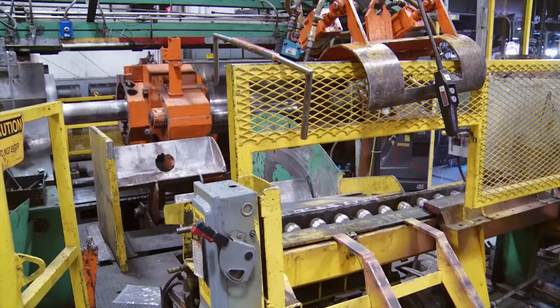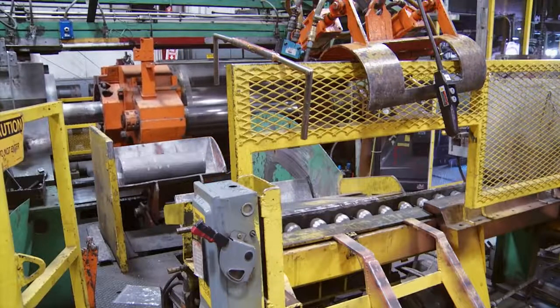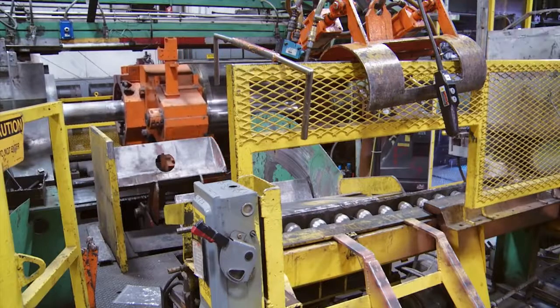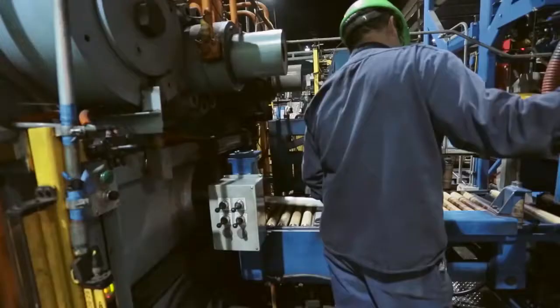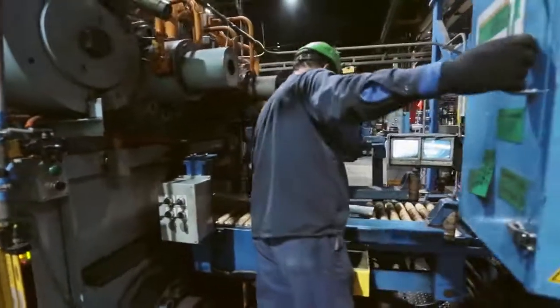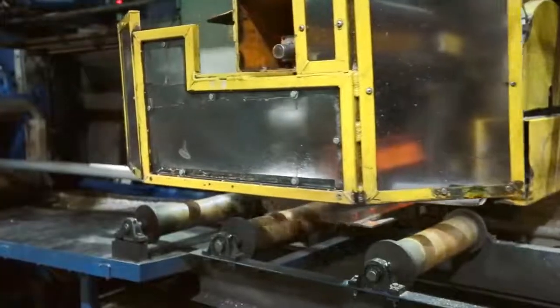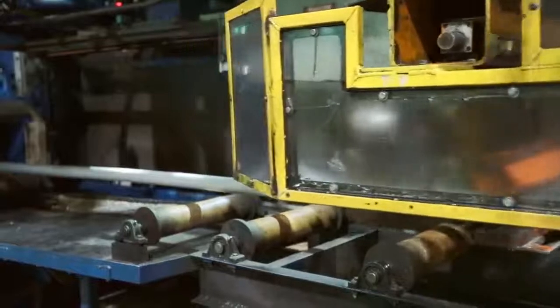Friction is a major energy cost of extrusion. Some calculations have friction accounting for half of the total energy drain on our business. Friction also robs die face pressure and can vary extrusion temperatures, which in turn affects dimensional control of the finished extrusion.